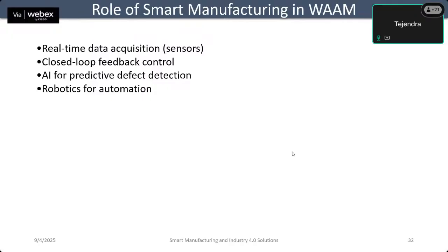Second is closed-loop feedback control. Instead of waiting until the part is finished, the system can make adjustments instantaneously, like changing the wire feed speed or the torch travel, so that the bead shape and quality remain consistent throughout. Artificial intelligence can also help in predictive defect detection. By analyzing past process data, it can forecast when or where porosity, cracks, or distortion can occur, and adjust before they actually happen.